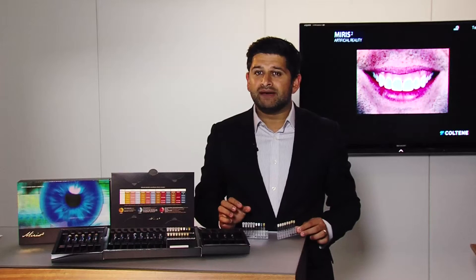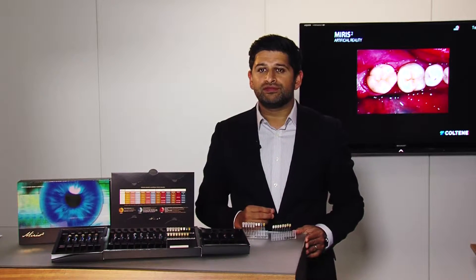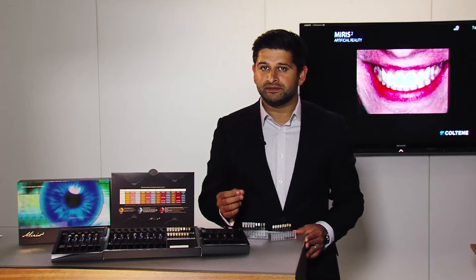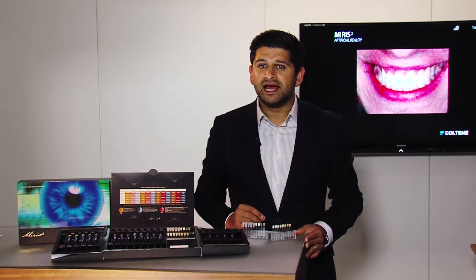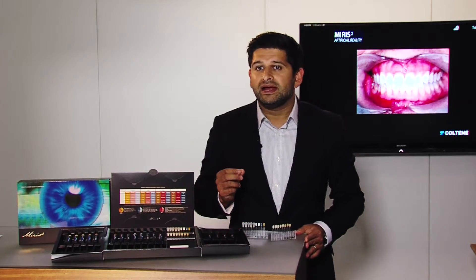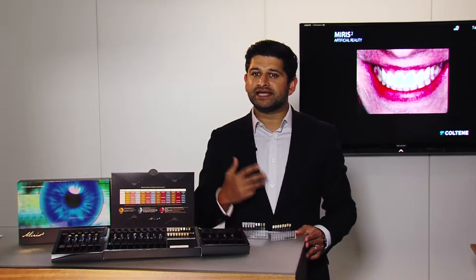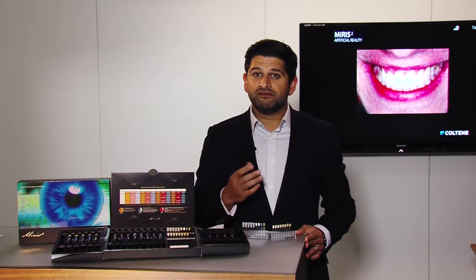The research found that enamel tremendously influenced the perception of colour. In natural enamel, differences in lightness and translucency proved to vary in relation to tooth age, and therefore three different types of enamel were described. First, young enamel, which had a white tint, a very high opalescence and less translucency. Adult enamel was the second type, which had a natural tint, less opalescence and an intermediate translucency. And then old enamel, which had a yellow tint and a higher translucency. To allow for some of these natural variations, five different types of enamels based on the above findings were made for Miris2.